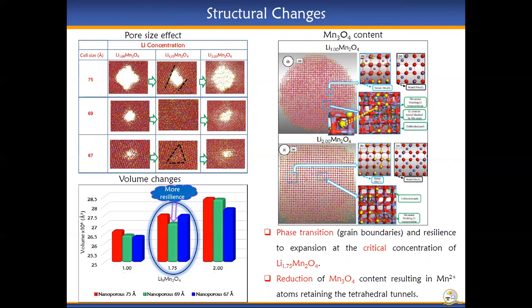Whereas for nanoporous 69 and 67, the pores completely closed up. However, all the structures regained their original pore size upon full lithiation at Li2.00Mn2O4 concentration.